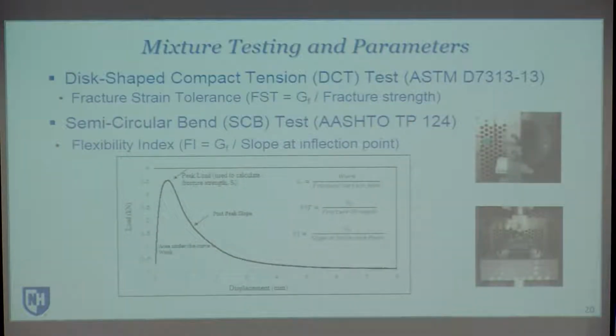For the disc-shaped compact tension test, okay, we're following the standard protocols, the ASTM standard, okay, and the testing is done at 10 degrees above the low temperature at which the material is expected to be placed in the field. So that test is conducted at different temperatures depending on the location that the material is going to be in the field. Okay, and the parameter that we're looking at there is what's called the fracture strain tolerance.